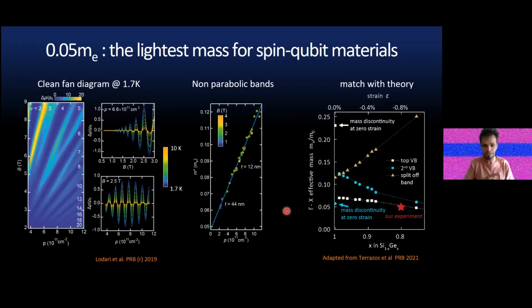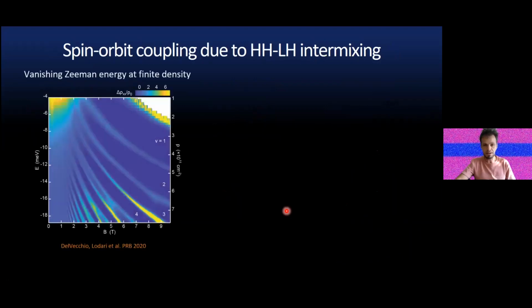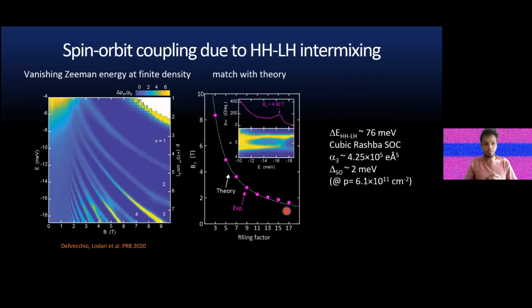So we've shown high mobilities, meaning low disorder. We've shown light effective mass. Another parameter that we can still get from transport measurements before going to quantum dots is the spin orbit coupling. This is a Rashba kind of spin orbit, and it's mainly due to intermixing between heavy holes and light holes at a finite density. We developed a very subtle but very nice, elegant method to measure the HH-LH splitting and in turn have an idea of the spin orbit coupling energy here.